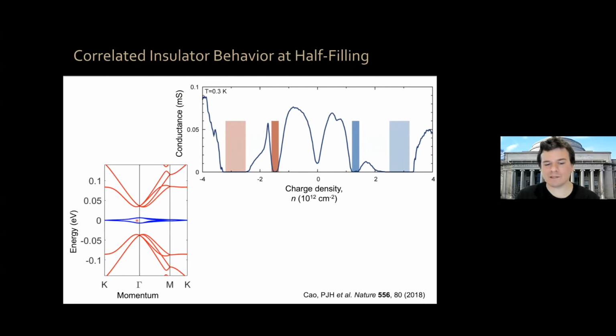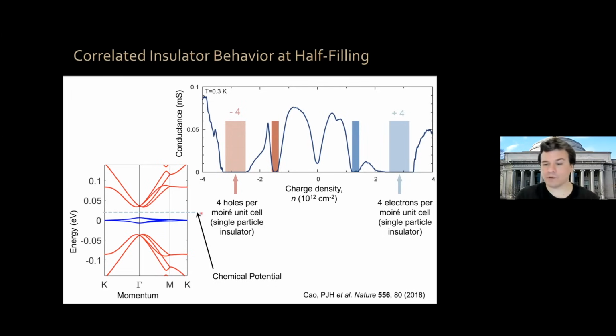Turns out, remember that I told you that in these flat bands, the electrons in twisted bilayer graphene can have this fourfold degeneracy: spin up, spin down, valley K, K prime. We also have 2 layers. It turns out in these flat bands, from bottom to top, you can put 8 electrons per Moiré unit cell, okay? So if we add to the system 4 holes per Moiré unit cell, or remove 4 electrons from charge neutrality, your chemical potential ends here. And as a result, because your chemical potential is in the middle of a band gap, you have a single particle insulator behavior, okay? This is exotic, but well understood in terms of single particle physics. The same thing happens if you put 4 electrons per Moiré unit cell. Your chemical potential goes here, you're in the middle of a band gap, and you have a single particle insulator.